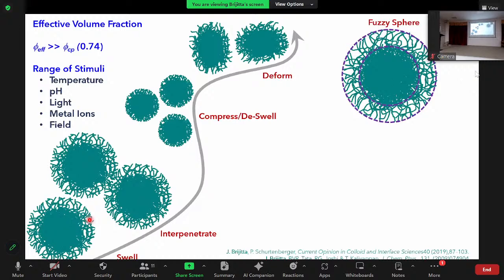Another important aspect of these microgels is that we synthesize these particles by free radical precipitation polymerization, and once the oligomer radical keeps growing, after a certain concentration they collapse, and the collapsed particles have a dense core, and then there are dangling ends which we call fuzziness. So these particles are generally represented not as hard spheres but as fuzzy spheres. In the upcoming slides, I am going to show you the results on poly N-isopropylacrylamide with acrylic acid. This part is temperature responsive, and this part is pH responsive.